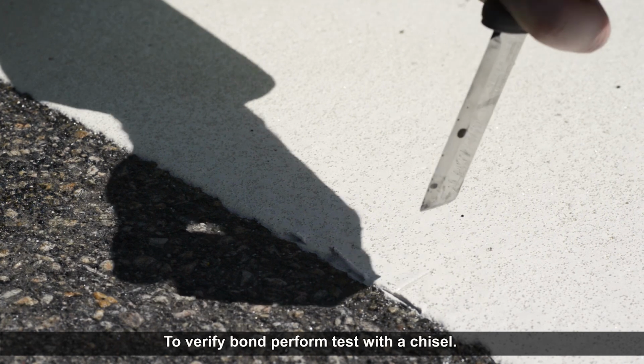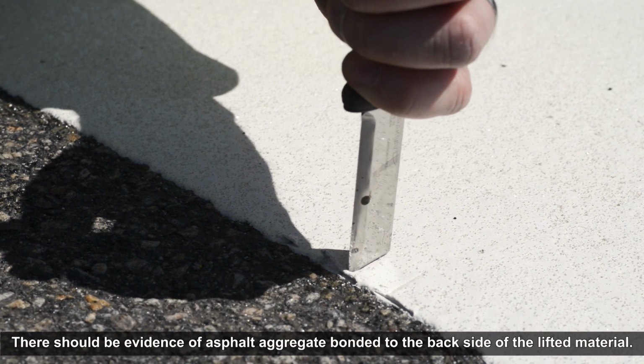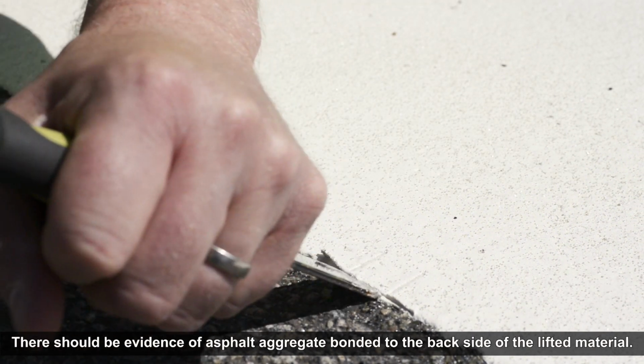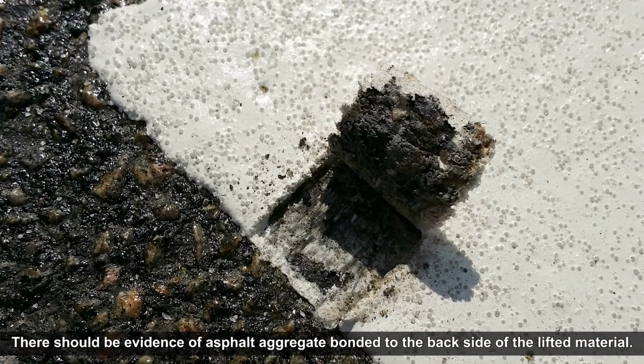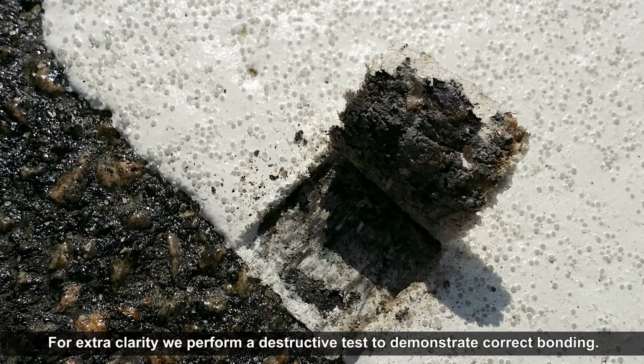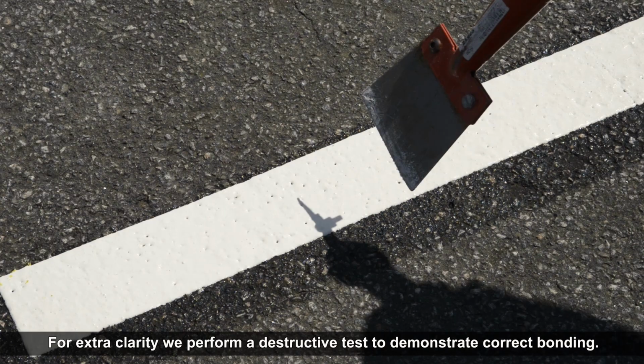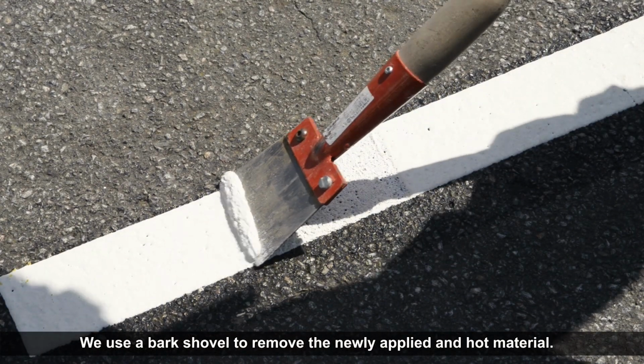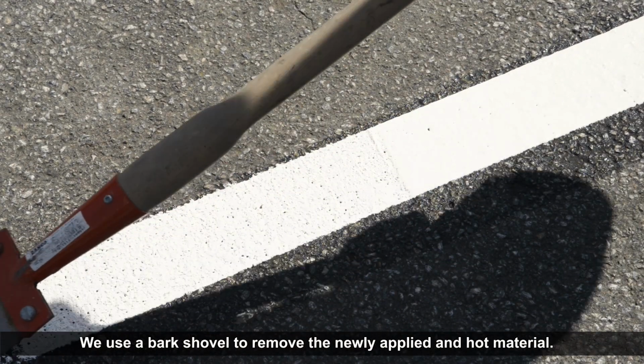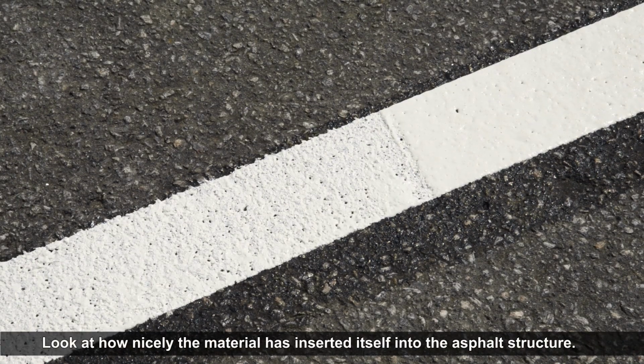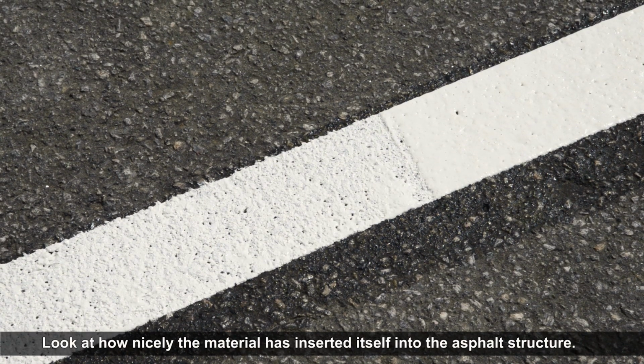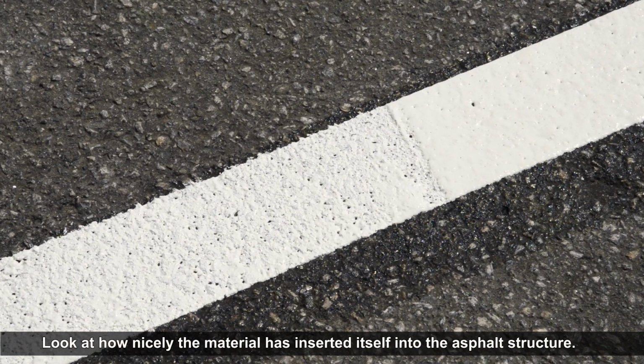To verify bond, perform test with a chisel. There should be evidence of asphalt aggregate bonded to the back side of the lifted material. For extra clarity, we perform a destructive test to demonstrate correct bonding. We use a bark shovel to remove the newly applied and hot material. Look at how nicely the material has inserted itself into the asphalt structure.